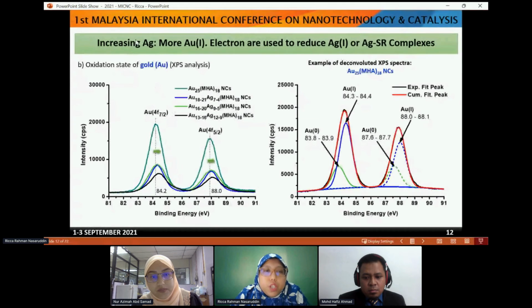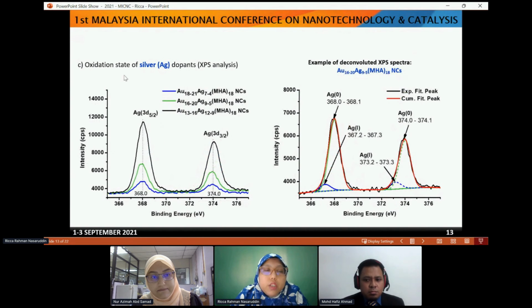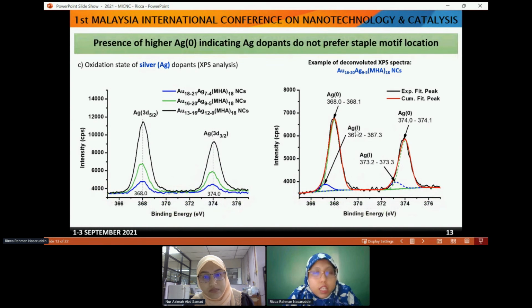Now, when we increase the silver, if you check here, there will be more Au1, because electrons are used to reduce Ag1 or the Ag-SR complex. So this is the oxidation state for silver dopants. Here is an example of the convoluted XPS spectra, and you can see it is quite different. When we add more silver, we see more silver 0 as compared to silver 1. So what does it mean? The presence of higher silver 0 indicates that the silver dopants do not prefer the staple motif location.